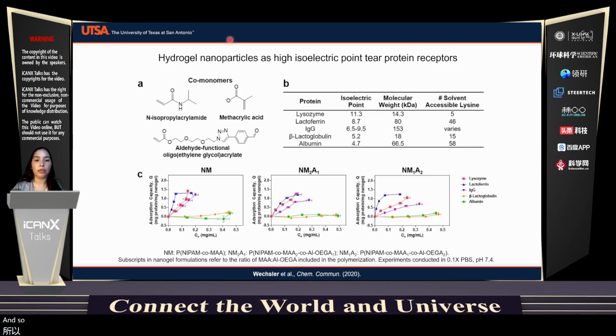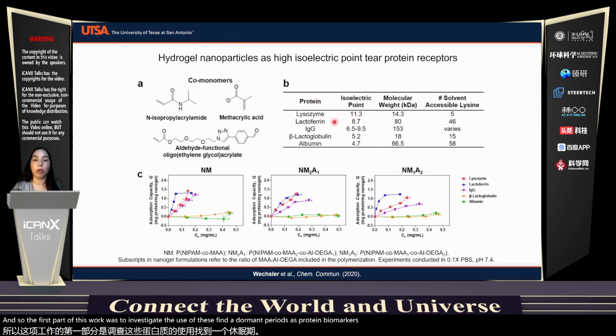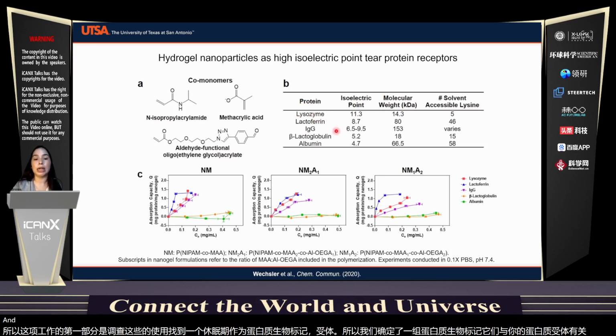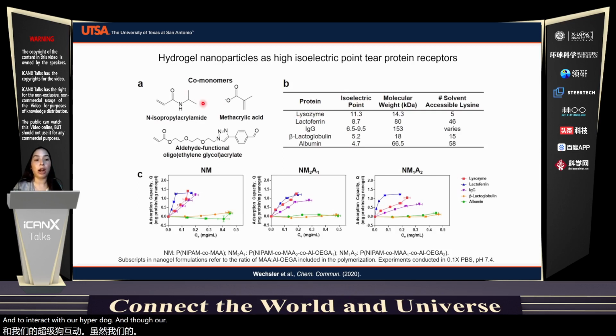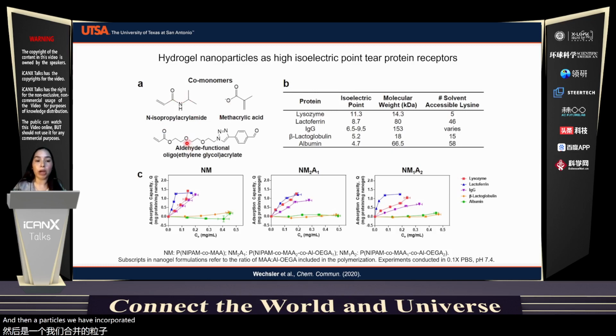And so the first part of this work was to investigate the use of these hydrogel materials as protein biomarker receptors. So we identified a set of protein biomarkers to interact with our hydrogels. And so our hydrogel nanoparticles are primarily based on N-isopropyl acrylamide, or NIPAM. They're copolymerized with methacrylic acid, which is our anionic component. So we're synthesizing negatively charged nanoparticles. We have incorporated a custom aldehyde functional oligoethylene glycol acrylate, or ALOEGA, monomer.